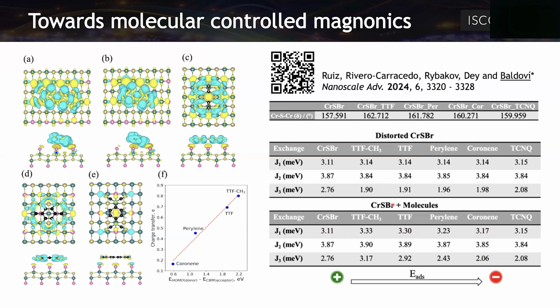And this is important because then it's related how this is going to affect the magnetic properties in the material. Well, in this case, we wanted also to check what happens with the structure. So when we have chromium sulfur bromide, we have this chemical bond along the b-axis by sulfur bridges of 158 degrees. And in all the cases, this is being enhanced by the presence of the molecule, except the TCNQ that is not affecting that much, but in general, all of them are affecting towards an increase of this bond. This is not good because this increase of the bond makes the J3 decrease.